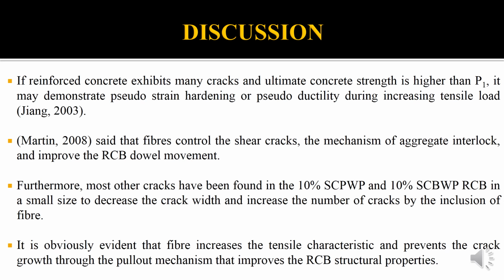This is the discussion. If reinforced concrete exhibits many cracks and ultimate concrete strength is higher than P1, it may demonstrate pseudo-strain hardening or pseudo-ductility during increasing tensile load, as stated by Jiang 2003. Martin 2008 said that fibers control the shear cracks, the mechanism of aggregate interlock, and improve the reinforced concrete beam dowel action. Furthermore, most other cracks have been found in the 10% shredded copier waste paper and 10% shredded cardboard waste paper reinforced concrete beams in a small size, decreasing the crack width and increasing the number of cracks by the inclusion of fiber. It is evident that fiber increases the tensile characteristic and prevents crack growth through the pull-out mechanism, which improves the reinforced concrete beam structural properties.